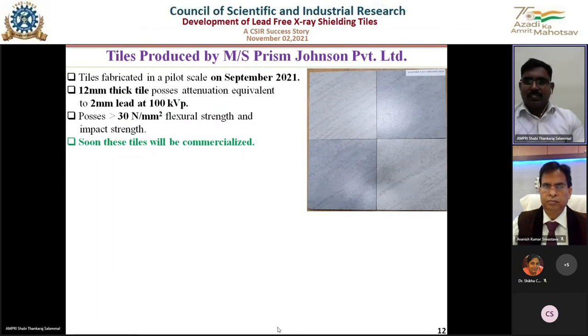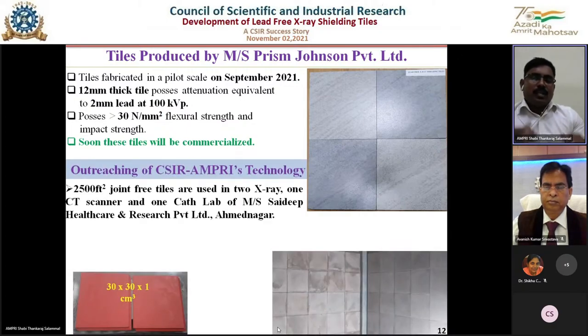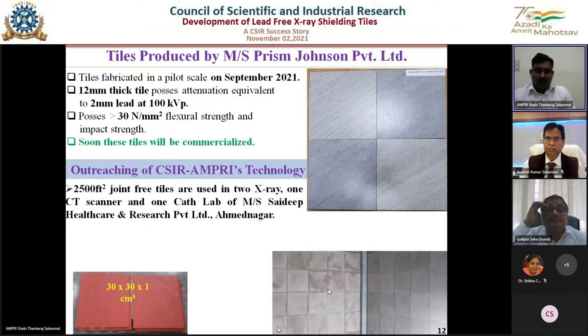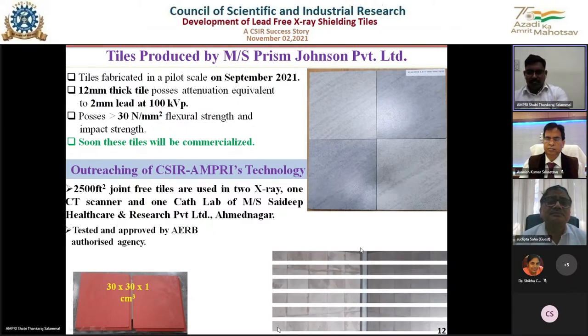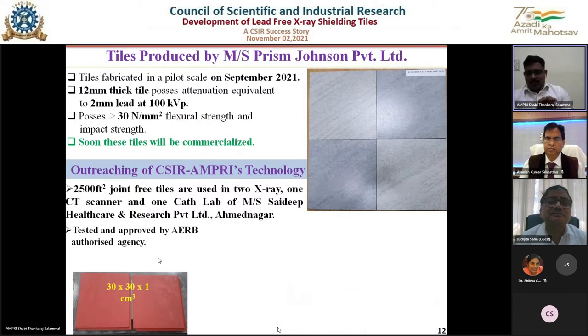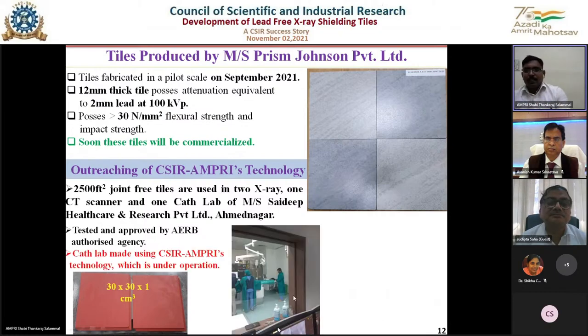And it possesses sufficient flexural strength as well as impact strength. And as an outreach of our technology, we have made joint-free tiles of nearly 2,500 square feet. We have put them on the wall of the Cath Lab in M/S Saideep Healthcare & Research Pvt. Ltd., Ahmednagar. After paving, these tiles were tested by AERB-approved agencies and found to be suitable for operation. So here you can see this Cath Lab, made using this technology, which is now in operation.